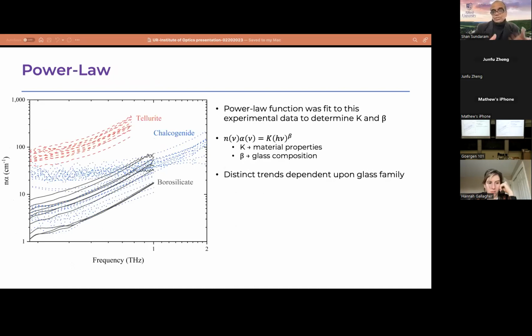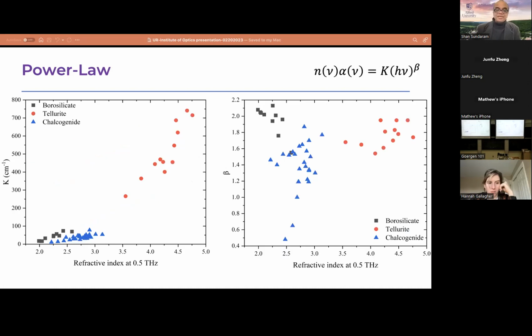And now we used all of our data set and we plugged it into this power law relationship, and we are showing you the refractive index times absorption coefficient as a function of frequency. And we wanted to extract the K material property and the beta, because the beta was reported to be 2 for all glasses. All the physics journals, glass journals said, oh, we sort of know the power law for glass, it should be 2. So we were also wondering why 2. We're trying to find out, and we found out it's really not entirely true. When you start looking at various families, the beta values change as well. So we are showing now the K values we calculate for all the glasses, and the beta values calculated for all these glasses from our data set.